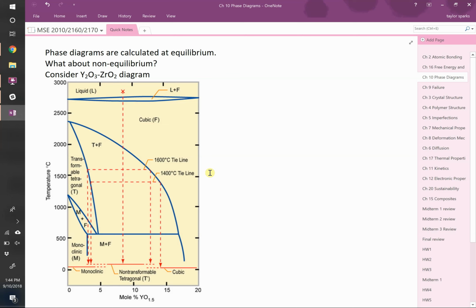It's a ceramic, so you can sharpen it very, very sharp, but because you have this T phase down here where it wants to turn into M, when a crack does start, that provides a little bit of energy that it needs for T to turn into M, and when it does so, this is amazing, it's a little bit of a volume expansion, and it closes the crack. Can you believe that actually works? That sounds like something my kid would come up with, like maybe make the phase expand and close the crack. Like, that works! It's incredible, right? So we're going to talk more about this later on. It's a metastable phase that kinetically is limited. It can't turn into the M phase until you give it a crack nearby. We'll talk about this more next time.